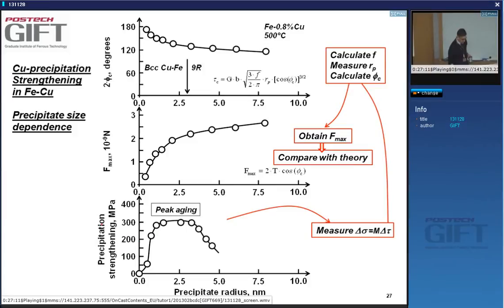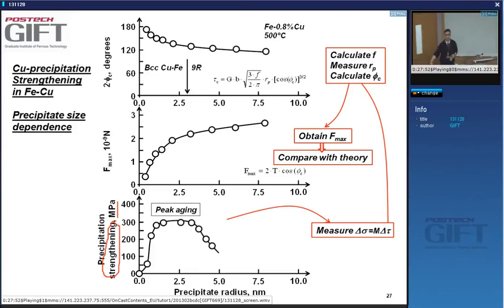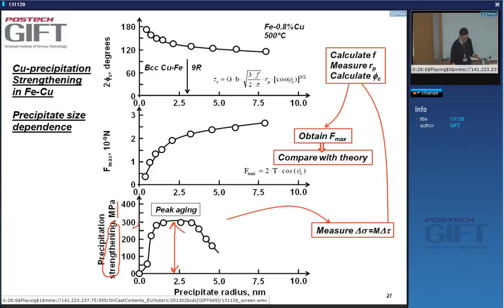Looking at more data: here the strengthening effect is in MPa from a tensile test, already converted as a function of precipitate radius. A maximum is reached and then decrease — the material is overaged. We took away all other strengthening contributions — solid solution, Peierls stress, grain size — leaving pure precipitate strengthening, and we find peak hardening is indeed around 300 MPa.